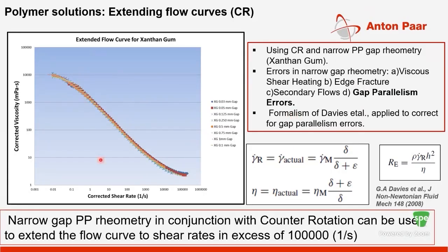The one thing we had to pay attention to was once you start going down to very, very small gaps, gap parallelism becomes a big issue, and that can throw the data off. So we used a formalism developed by Davies et al., published in the Journal of Non-Newtonian Fluid Mechanics.